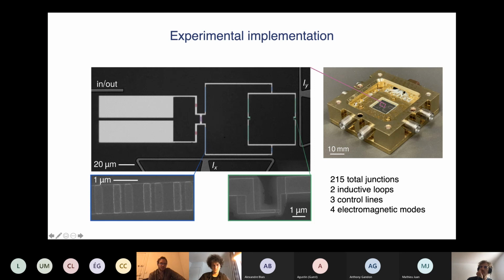But I don't think this is a very hard limit. You can imagine doing other types of junctions. First of all, you can imagine evaporating multi-layered oxide, just to increase the thickness of the junction oxide. You can also imagine doing things like nanowire junctions or granular aluminum junctions, where the insulating layer is actually extended instead of just being a thin oxide. That's great. Thanks a lot for the answer. I understand.